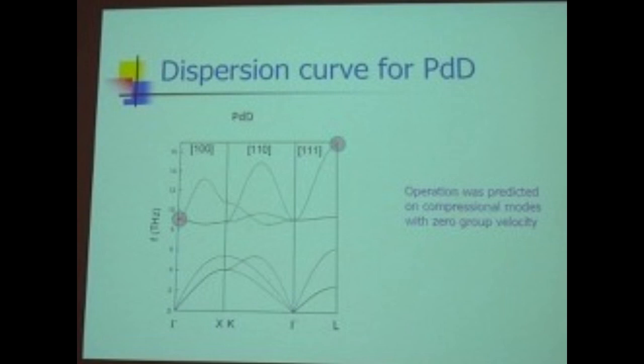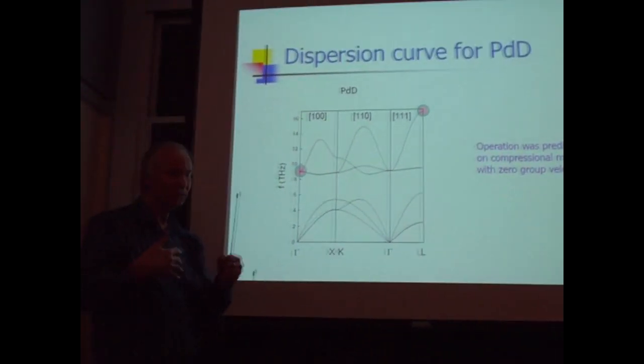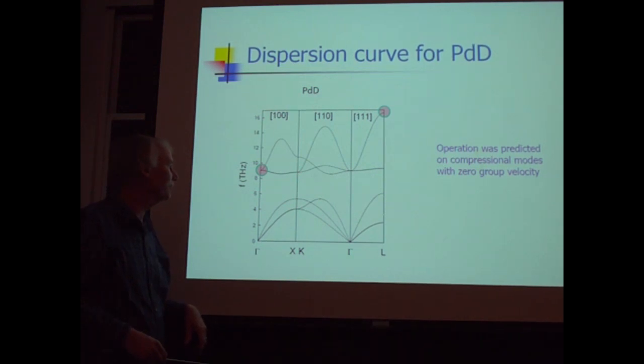Here's the spectrum that we'd talked about earlier on Monday when we were explaining that condensed matter had nothing to do with cold fusion whatsoever. These are acoustical phonon modes, basically vibrational waves going into the metal, at relatively low frequency, 6 terahertz and under. Well, it's actually very high frequency in the grand scheme of things, but these are considered acoustical phonons. Palladium is doing the moving, and the hydrogen in between is moving along with the palladium primarily. So there's order between the motion of the light interstitials and the heavier metal atoms.